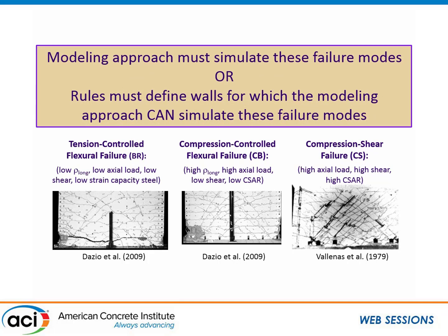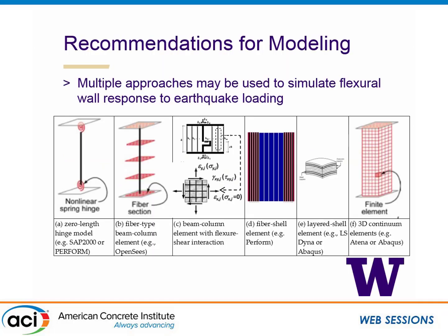The compression-shear failure is really where shear and flexural demands interact to cause a very large compressive demand, and you get crushing within the web where there might be less confinement and less longitudinal reinforcement. Given these different failure modes, we're looking for modeling techniques that either simulate these failure modes explicitly, or rules that tell us which failure mode is appropriate. There are a number of ways of modeling RC walls — from lumped plasticity through continuum — including lumped plasticity, distributed fiber-type models, fiber-type hinges, and a perform wall model.